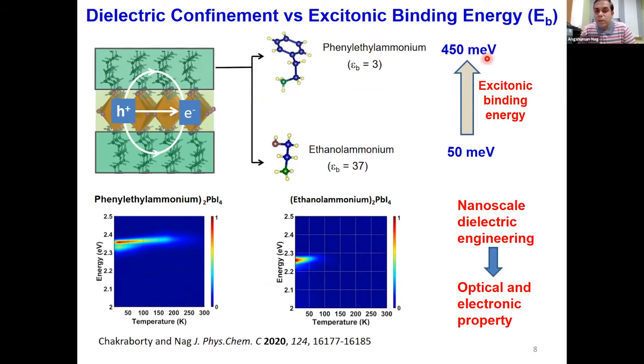Now, this high excitonic binding energy is good for recombination of excitons and therefore for properties like LEDs. However, if you change the organic layer to something like ethanol ammonium, then you get a higher dielectric constant for the barrier, and this reduces the excitonic binding energy to only about 50 meV. So there's an order of magnitude change in the excitonic binding energy. We know that typically excitonic binding energy is an intrinsic property of a semiconductor, and here you can play over an order of magnitude in terms of excitonic binding energy just by changing the organic layer. And this gives a tremendous opportunity to look for different optical and optoelectronic properties.